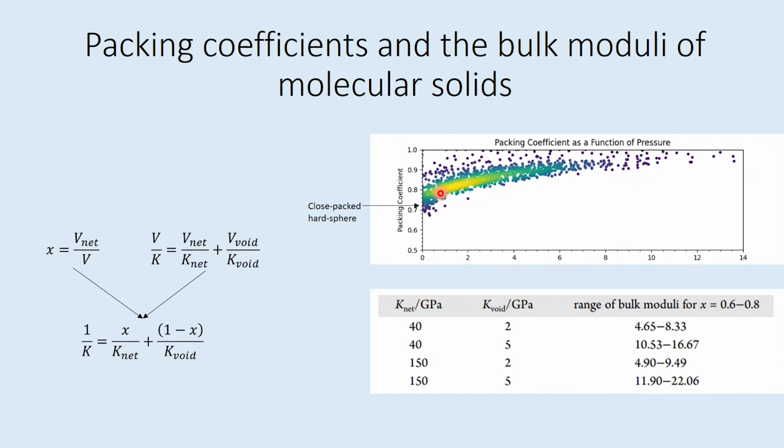Yeah, so at transitions, we tend to look at bulk moduli changes. They are very subtle, and annoyingly, sometimes you get some really nice discontinuities and you do some DFT on it and they disappear, which is not helpful. But we normally look at bulk moduli as an indication of a change at a phase transition. So we try and fit equations of state before and after the transition. A change of more than about 10 GPa is potentially significant, but more than anything, they're indications of a need to go and find those transitions.